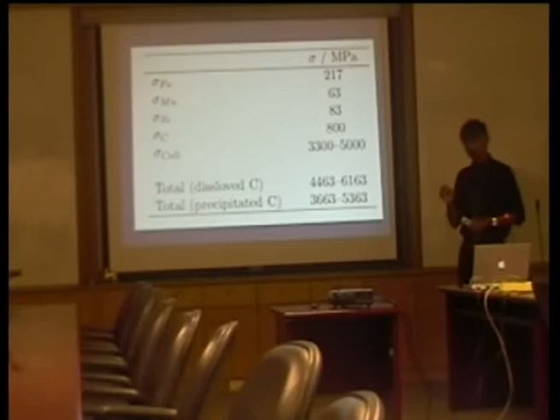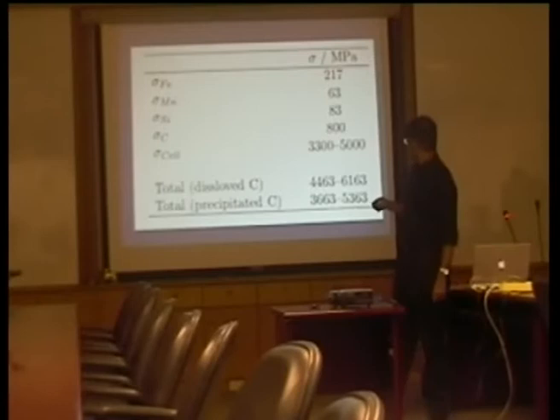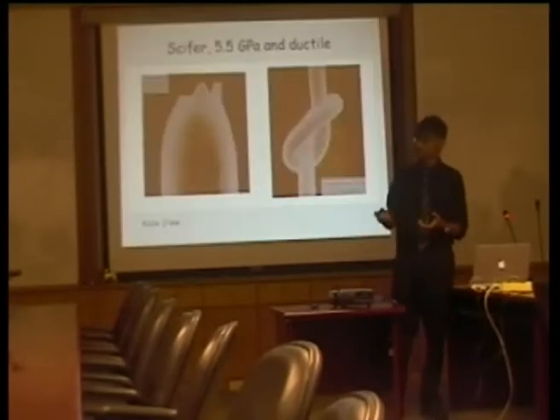So we are getting our strength mostly from the grain size effect, in that we have reduced the grain size to 10 to 15 nanometers, and that is causing a major increase in strength. If carbon was actually contributing that much, we would get a much higher strength level in our steel. It is likely that some of that carbon is precipitated. I'll show you some evidence.